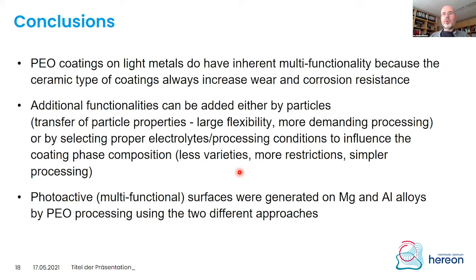But however, particles in PEO processing are more demanding from the PEO side. And from that point of view, one always has to think. Having an alternative, for example, to functionalize the coating directly from a simple electrolyte is from an industrial point of view much more promising. But however, you see, you have less variety when you try to do this. You are more restricted in the selection of substrate and of electrolytes, but you have a much simpler PEO processing. And finally, photoactive surfaces can be generated on magnesium and aluminum alloys using the PEO process. So thank you very much for your attention.